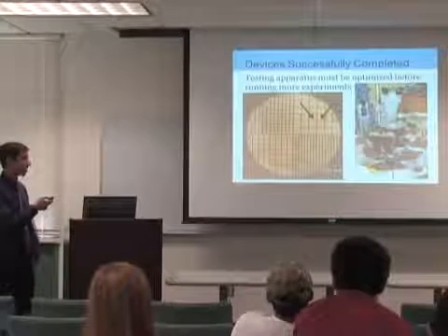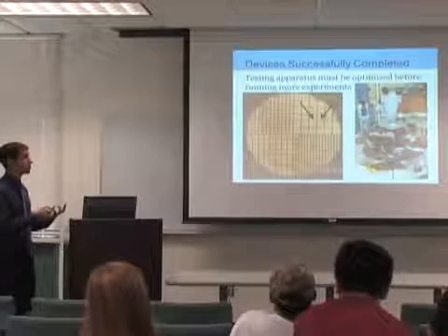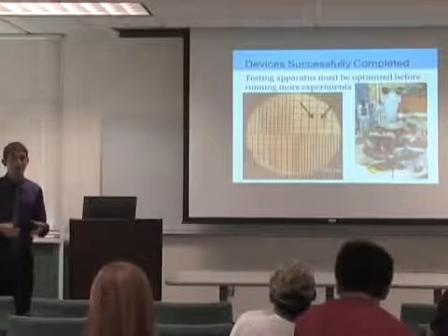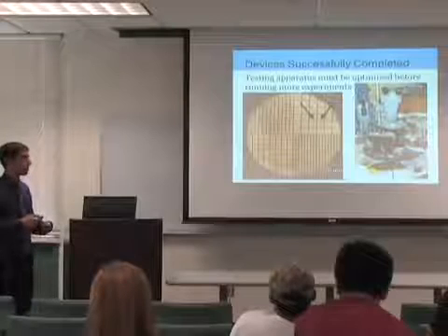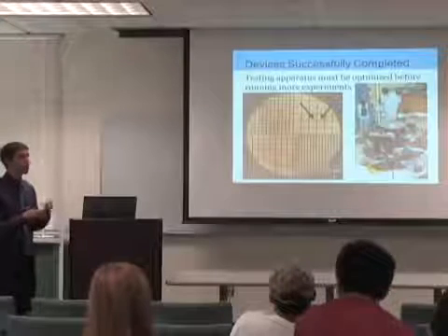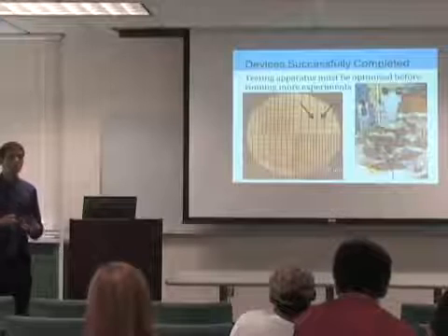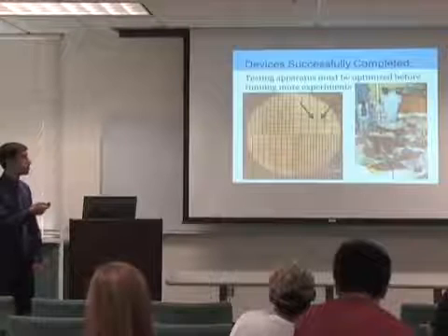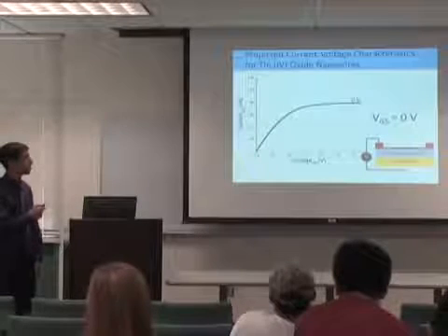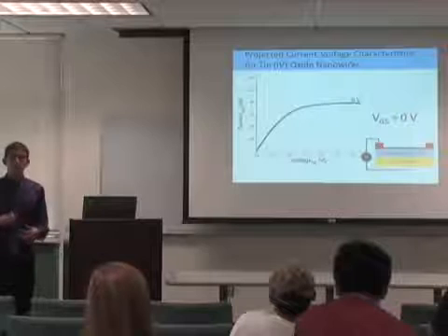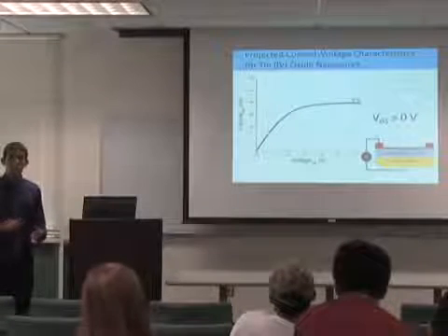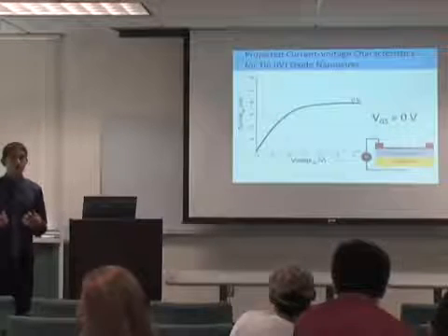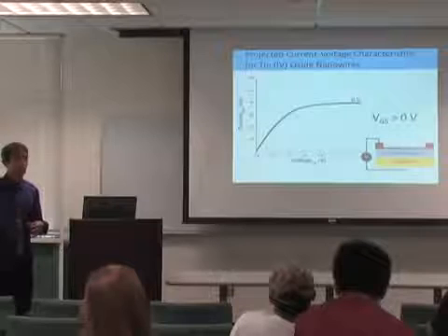Although currently we are facing some challenges with this testing apparatus, mostly because we're working with such small currents around the nanoamp range, we hope to overcome these challenges and continue with our electrical measurements on these devices. As of now, we do have a projection of what that should look like. Here we have a nice projection of the current-voltage characteristics of these tin oxide nanowires. This is without any gold nanoparticles, so without any influence of the surface plasmon resonance that we hope to see down the road.